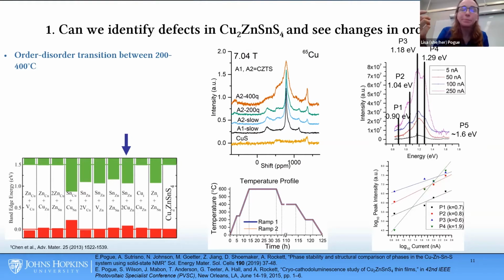And that is very important for solar cell performance because the disordered material tends not to produce as high efficiencies in devices compared to the ordered structure. So it's important when you're cooling your device down after your initial film synthesis to dwell at a temperature such that the material can reorder and be more efficient.